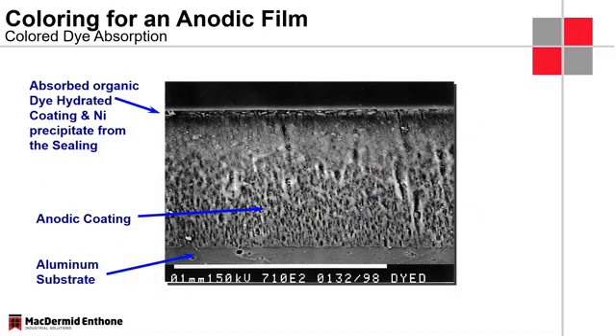So when we look at a cross section here, and I hope everyone can see that, maybe we'll go from the bottom here. We see the aluminum substrate with a clear dividing line. Then we have a porous anodic coating, and then we see the part where we don't really see these cavities or these channels anymore. This is really the sealed surface where the pores swell and they close up. And then right at the top, we actually see the organic dyes. So these are obviously the immersion dyes, and they're really only in the top part of this anodized layer.